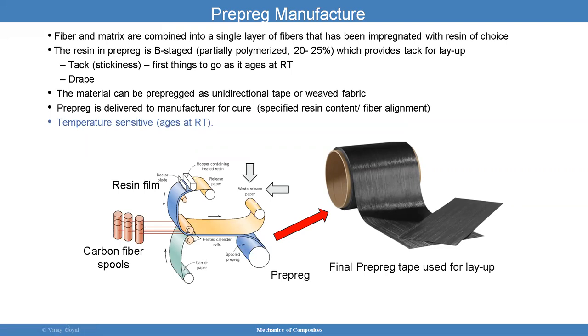You can see this prepreg will be flexible enough. The resin in prepreg is B stage. What I mean by B stage is that it has gone through some polymerization, and that provides some tack for the layup, and it will be sticky. So I can then take layers of this, cut them up at different angles. Here we cut a layer out, or a lamina, and I can cut more of this and stack them up. And you'll have some stickiness. The reason it's sticky is because you have a partial cure. It's not fully cured, so things can still flow when I heat them up.